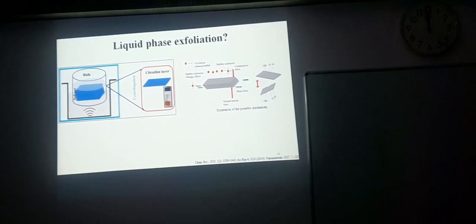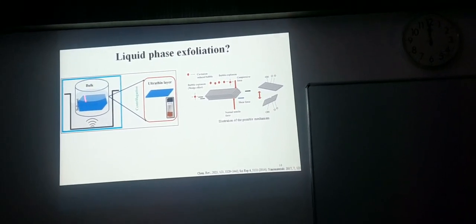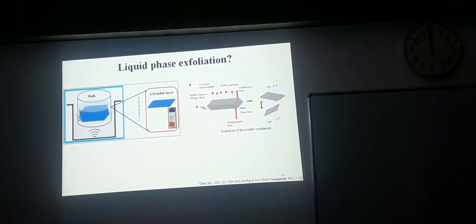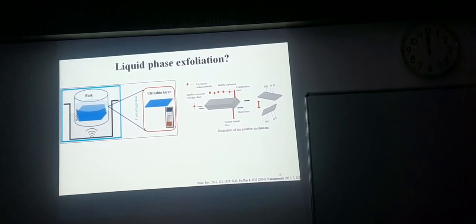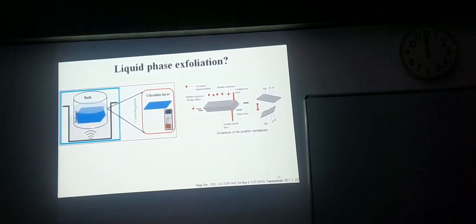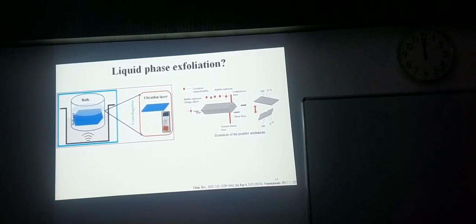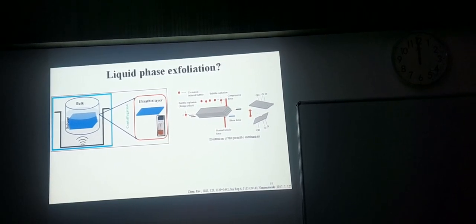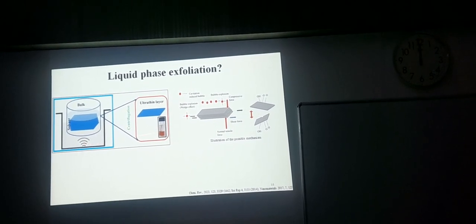Here is the schematic of liquid phase exfoliation. It is very simple but very critical, because we use a liquid to exfoliate this 2D material. Just a short introduction: the bulk crystal of this 2D material is poured into a solvent, and we use ultrasonication to create some forces. You can see here the whole schematic. When you produce this ultrasonic sound, it can create some bubbles.